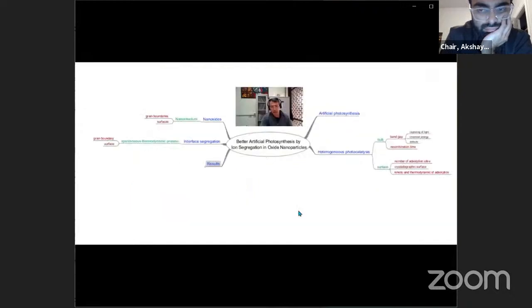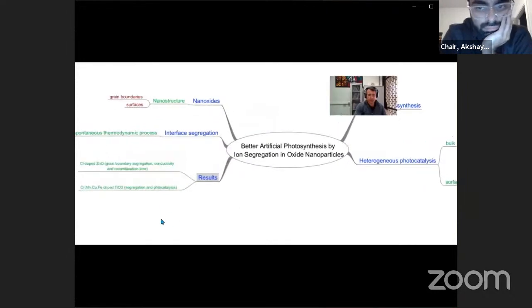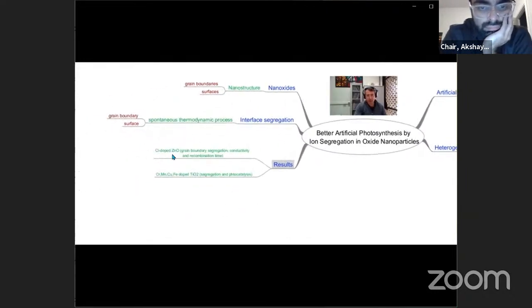Now I want to show you some results about our work in photocatalysis and try to connect the surface segregation with photocatalysis and how this photocatalysis could be better with ion segregation. Then we have 2 works. One is the segregation of chlorine in zinc oxide grain boundaries, then the change in the conductivity and the increase of recombination time, and the consequences in the photocatalysis. And the second group of results is the transition metals doped titanium oxide, then the segregation and photocatalysis.